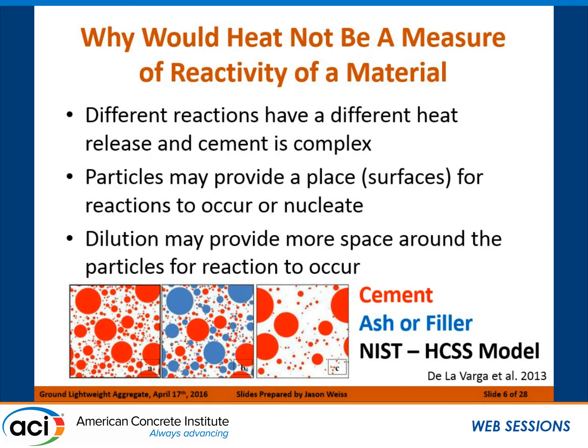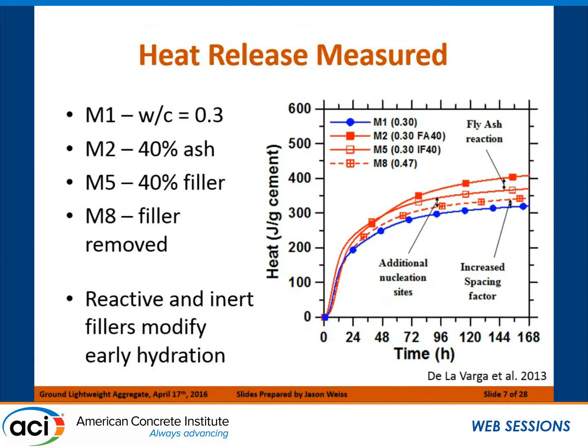Now if you take the filler out, or take the ash out, you have a system that has a lot more room, and you're going to have differences in reaction. The whole idea behind this was that we could tailor systems. We looked at a typical 0.3 water-to-cement ratio system, shown here in blue, a system with fly ash, shown here as M2 with the dark line, then two cases where we put in a quartz filler, and then a case where we simply remove the filler. In each one of those cases, we have a different overall heat release.